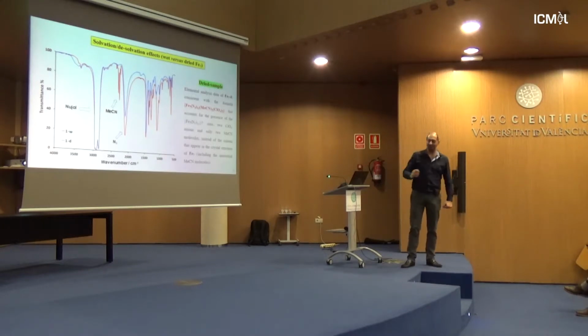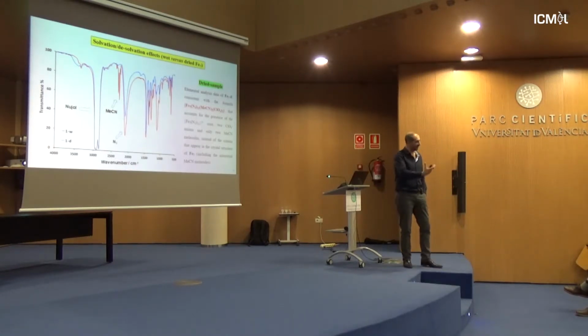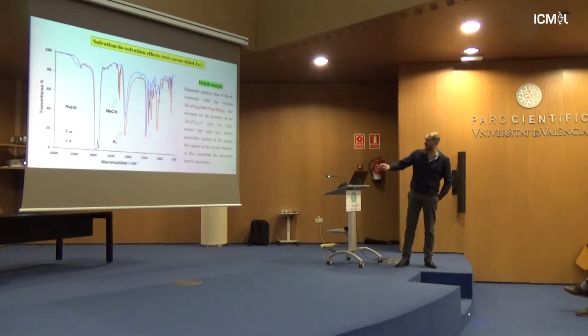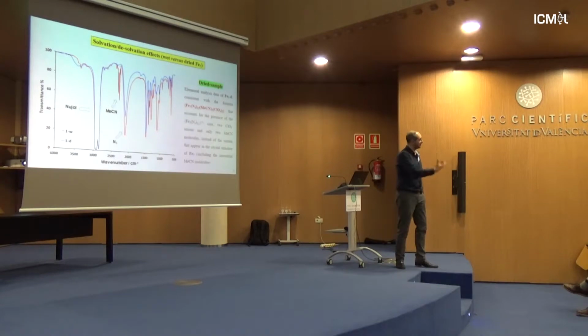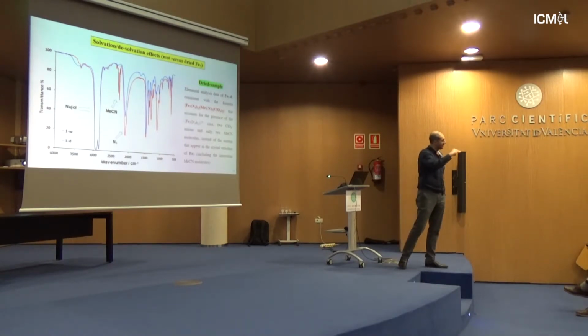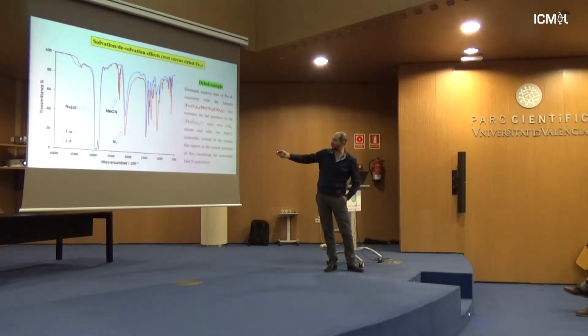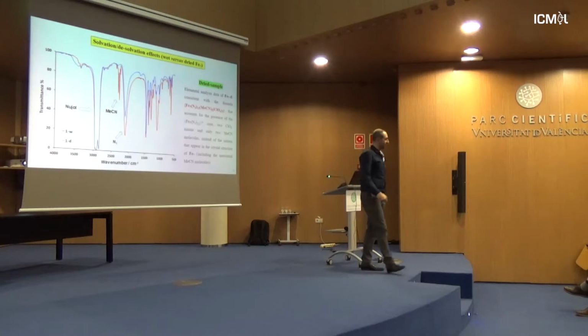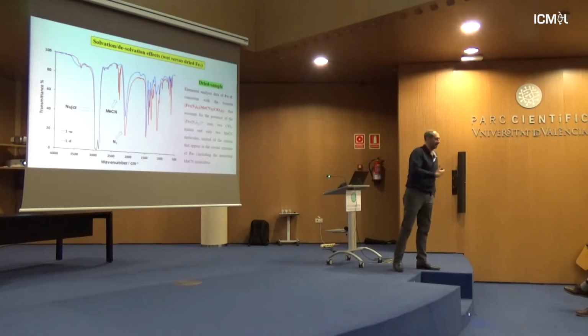But the IR was actually really good. Just forget those bands here, these are the Nujol bands from the way that we prepare the sample. We see that the wet compound, shown here in red, shows all the bands which correspond to the crystal formula of the compound, including the bands which arise from the acetonitrile molecules. When you leave the crystals in the glove box, exposed, then you slowly see that all of these acetonitrile bands disappear. So something new happens.